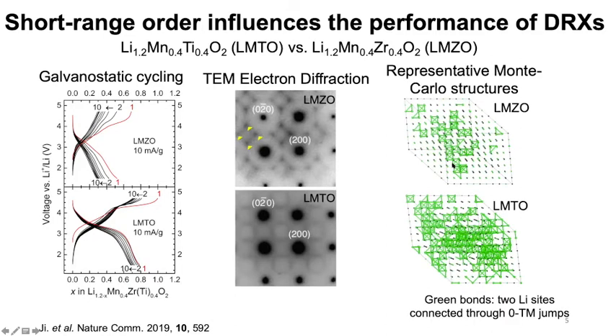And the difference in short-range order and electrochemical performance is further corroborated by Monte Carlo simulations. Here in the simulation results, the lithium connected to the 0TM migration path are connected with these green bonds in the figure. As we can see, LMZO has significantly less 0TM-connected lithium because of this unfavorable short-range order, while LMTO has more 0TM-connected lithium because of the other type of short-range order.